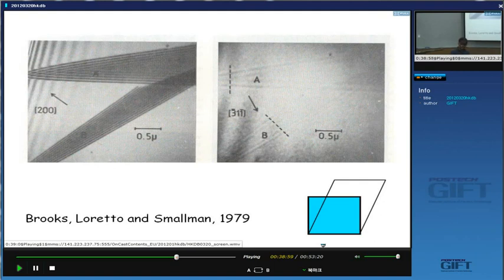So this is the first ever experiment which proves, first of all, that a single stacking fault can be regarded as epsilon martensite, a nucleus of epsilon martensite. So if you have a perfect dislocation which is a/2 [1 1 0], and it dissociates into partials, then in between the partials, you've created epsilon martensite.